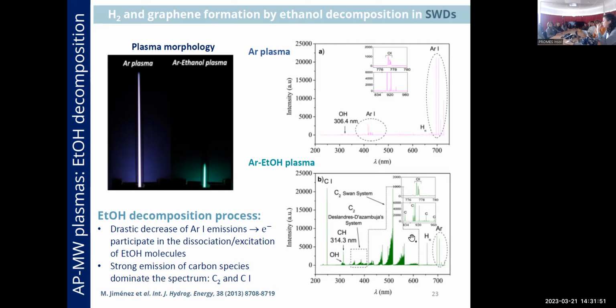Because the regular excitation-ionization process is completely destroyed. We introduce ethanol molecules, and our electrons, instead of being used to excite atoms, are used for decomposing the molecule. So we are going to have carbon, oxygen, and hydrogen atoms in our discharge. How do we know that? Because in the emission spectrum, we can observe emission of atomic carbon lines and also hydrogen lines. But it is also possible to observe molecular bands belonging to C2. So from the radiation, we can say that at least we are decomposing some amount of the ethanol molecules that we are introducing.